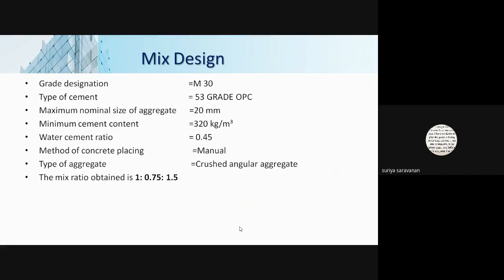The grade designation is M30 concrete, the type of cement is OPC 53 grade, and the nominal size of aggregate is 20 mm. The minimum cement content for M30 is 320 kg per cubic meter, and the water cement ratio we have adopted here is 0.45. We have placed this concrete manually, and the mix ratio we got is 1 : 0.75 : 1.5.